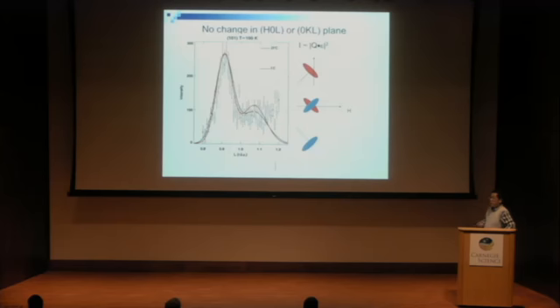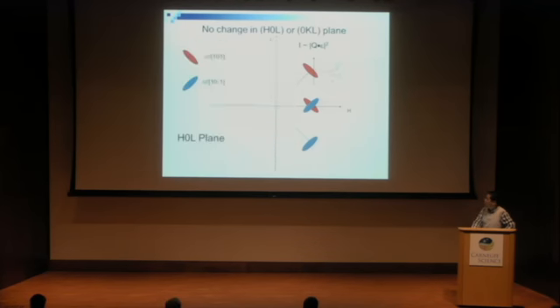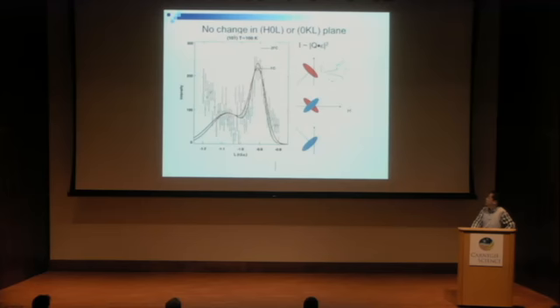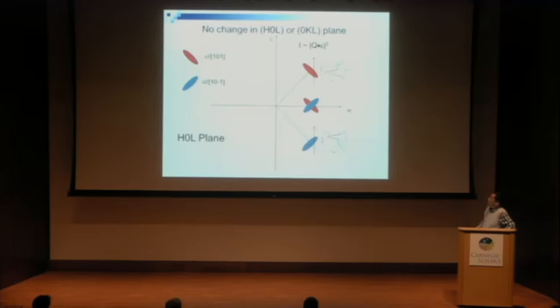By applying the same 110 direction electric field, the field could have no clear effect compared to the zero field cool data. It's the case for both the 110 bright peak and the 1-10 bright peak. So it seems the 110 field has no effect on diffuse scattering coming from either the 101 polarization or the 10-1 polarization. And it's also the same if we measure in the 0KL plane. So the 110 field has no effect on these four kinds of local diffuse scattering from local polarization.